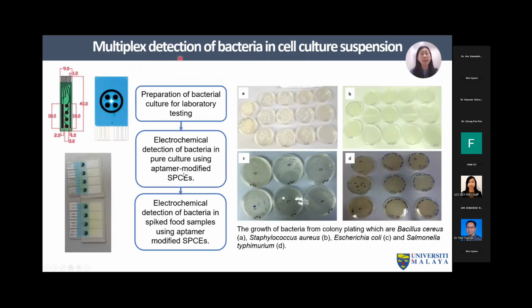This slide shows the multiplex detection of bacteria in cell culture suspensions. We can detect multiple bacteria at the same time. This shows a strip with 4 working electrodes, which means you can detect 4 bacteria at the same time. Here shows a different model of the strips. For the preparation of bacterial culture for lab testing, we will first use pure cultures, followed by food samples which have been spiked with a bacterial strain. After testing the sample with the developed biosensor, we will further verify the result using gold standard methods, including bacterial plating and qPCR.